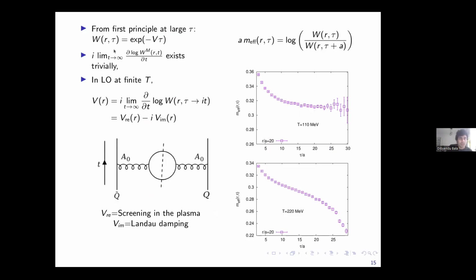It's from very first principles that at zero temperature, this Wilson loop just goes like the exponential of minus some number times tau, from a transfer matrix argument. This is a pure exponential decay at large tau. Therefore, the potential, this quantity inside the exponential, can be extracted by looking into the following quantity, called the effective mass. It's basically the ratio of the loop at tau divided by the loop at tau plus a. If pure exponential behavior dominates in the correlation function, this ratio will show a constant behavior in tau.